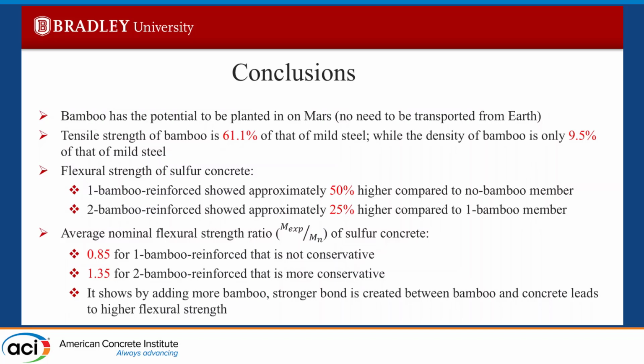And the flexural strength of sulfur concrete with one reinforced bamboo showed approximately 50% higher compared to no bamboo. So as you go from no bamboo to one bamboo, you'll see a 50% increase in that flexural strength, which is showing that this bamboo is actually working for the flexural strength. And as we go from one bamboo to two bamboo, that increases as well by 25%, which further proves that the more bamboo you add, the more it's able to withstand.